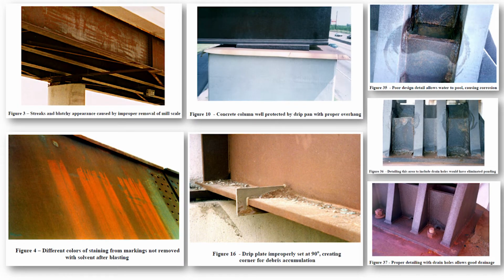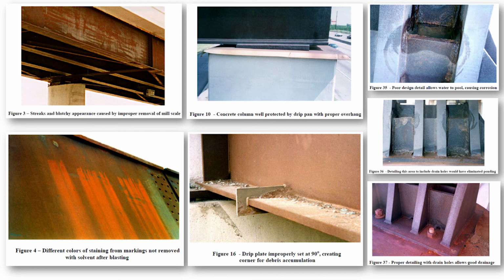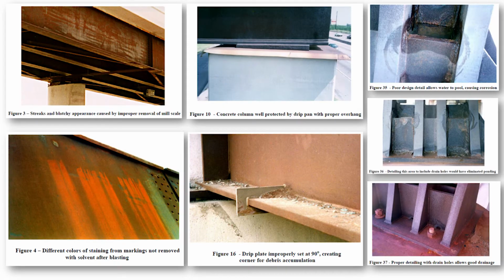We also looked at this bearing on the right, which is a bearing for a railroad bridge, CSX over Interstate 10 in Houston. And we saw stains coming off there, so we went up and looked. What we saw, if you look in the top right, is that there's water in between the stiffeners. There are weep holes at the bottom of the stiffeners, but in the middle picture you can see they're plugged with grime. So the grime plugs the weep hole, the water collects in there, and then you've got a big durability problem, right?